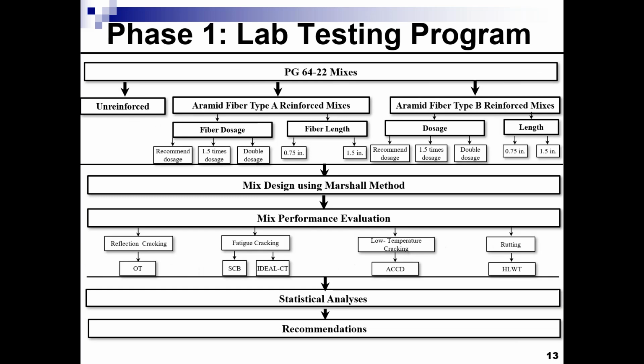And we did statistical analysis to compare the properties of the different mixes. If we want to get a closer look at what dosages and what lengths we have, we started with two different lengths, which is 0.75 inch, which is 19 millimeter, and then double that, which is an inch and a half. So we have two different fiber lengths. We also used the dosage recommended by the fiber supplier. And for both types of fiber, a very important thing is the Aramid fiber dosage was the same, which is 2.1 ounce per ton of mix.